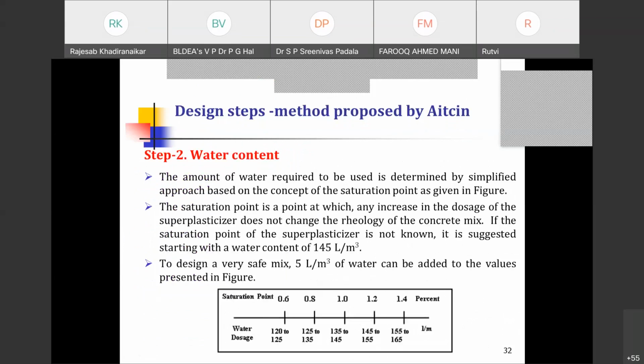So what is the step? From the first graph you choose the water binder ratio, and once you choose the water binder ratio or water cement ratio, then we have to find out how much is the water content. The amount of water required is determined by a simplified approach based on the concept of saturation point. They have proposed one graph here, and based on that you can decide how much initial water is to be added. So saturation 0.6, then 120 to 125, and up to 1.4, 155 to 165 liters per cubic meter. It is only a beginning point, as I said.